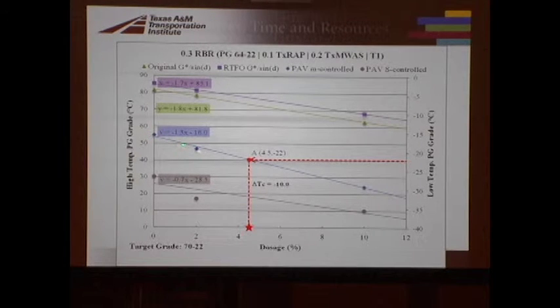So we add it in until we get to a minus 22, okay? Because we started off at a minus 15 or so. We got to add in recycling agent until we get to a minus 22, because our target is 70 minus 22. That's what we're trying to get to. That would be like if we just had virgin binder. That's what we're trying to get to. So when we get to minus 22, we have a dosage of 4.5%. That sounds reasonable. And we look at what our delta TC value is, minus 10.